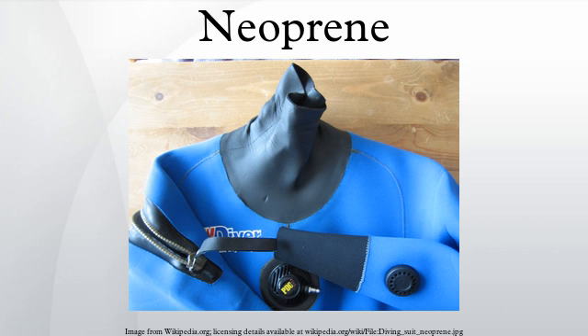The foam cells thus created also make the material quite buoyant, and the diver must compensate for this by wearing weights. Thick wetsuits made at the extreme end of their cold water protection are usually made of 7 mm thick neoprene. Since foam neoprene contains gas pockets, the material compresses under water pressure, getting thinner at greater depths. A 7 mm neoprene wetsuit offers much less exposure protection under 100 feet of water than at the surface.